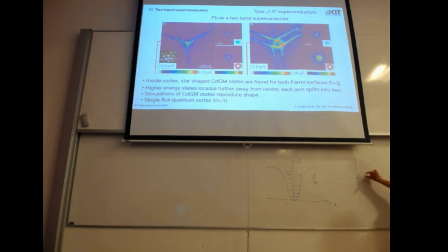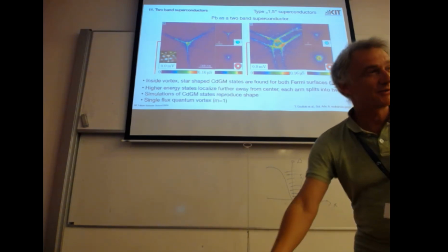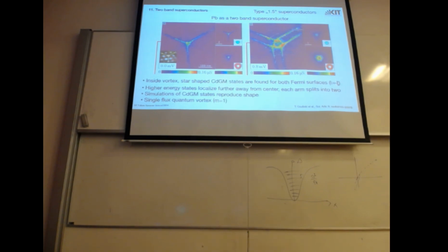And this energy spacing is delta squared over EF. So it's the gap divided by the ratio of this superconducting gap and thermal energy. It's like 1/10,000th of the energy, roughly speaking, and we don't have the energy resolution to distinguish those two states. So you would need something like nanokelvins with spectroscopic measurements to decide which one it is.